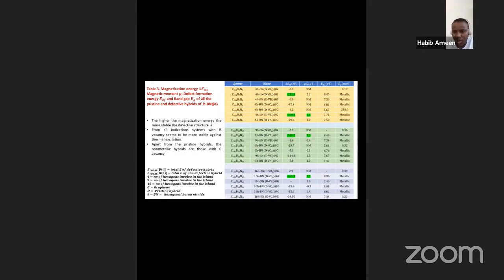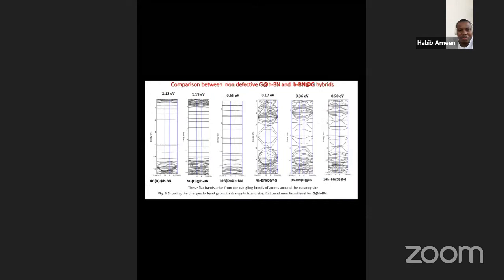Okay, and also how the band gap changes. You can see clearly the band gap changes: the bigger the island size, the smaller the band gap. For a visual comparison, the first three are the ones with graphene substrate and hBN island, the ones with the flat band gap. The last three, with these contours, are the ones with the hBN substrate and graphene island.